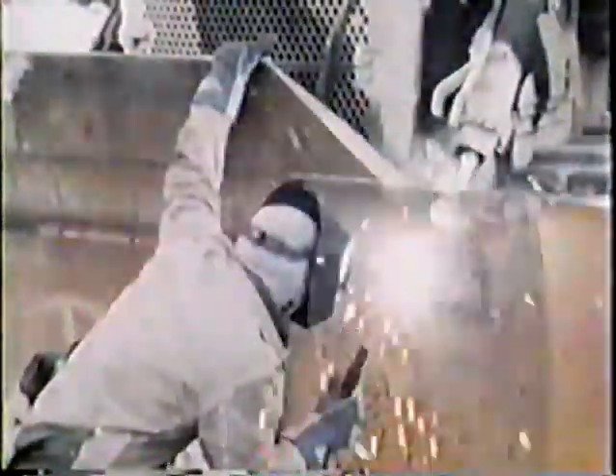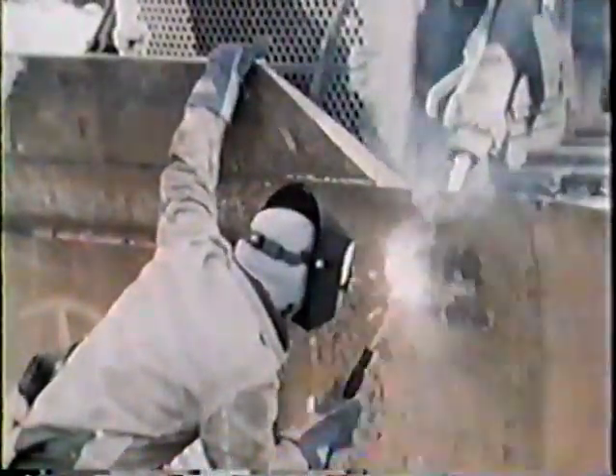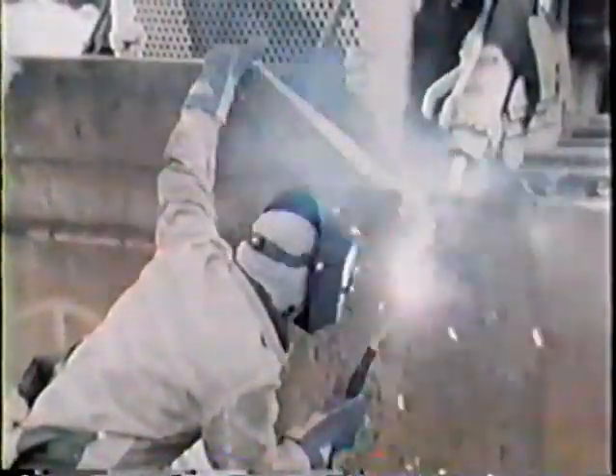Control welding heat by depositing metal in small string or tempering beads. Lay down beads 1 to 2 inches in length, starting at the root and toe of the groove. Avoid excessive puddling, because this will pick up carbon from the base metal, which, as we've seen, will make the weld metal hard and brittle. Confine the fusion between the filler and the base metal sidewalls to a narrow zone. Immediately peen the bead while the metal is still hot to overcome cooling stresses.